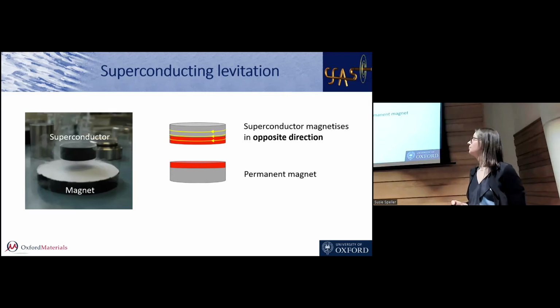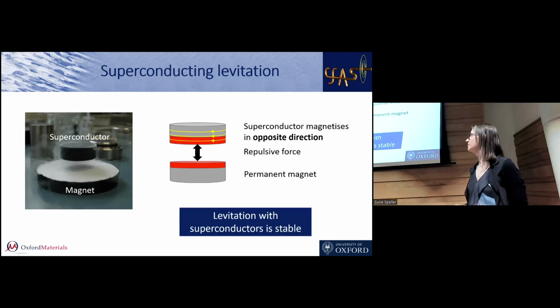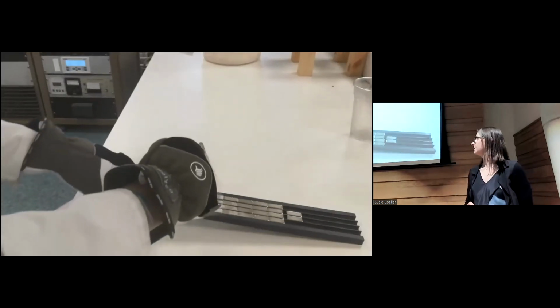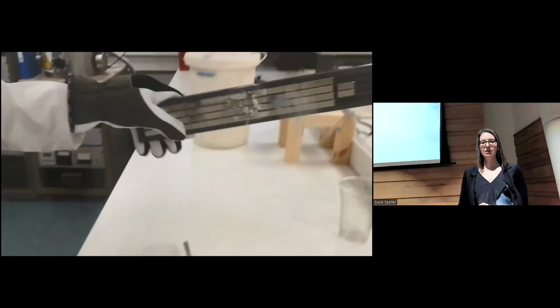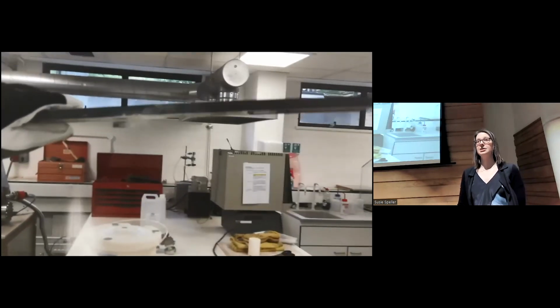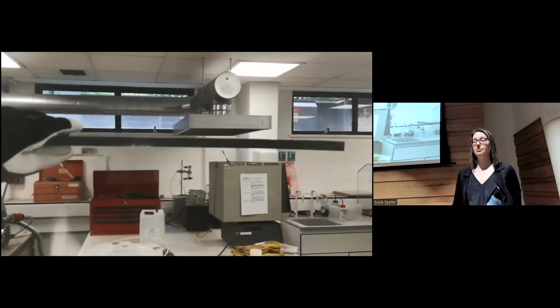And if we turned that superconductor over, the north pole would still be down, even if the superconductor was the other way up. So it's going to be stable. Okay, it's always going to be repulsive. It's never going to attract. There's a much more stable kind of levitation with superconductors. And it's even better than that. So now we've got a magnetic track down the bottom here, and we're going to float a superconductor on top of it. If we do it in the right way, you can turn the whole thing over and it just stays put. So it's really stable.